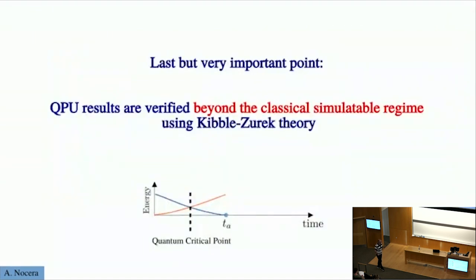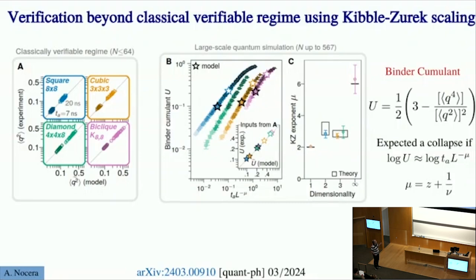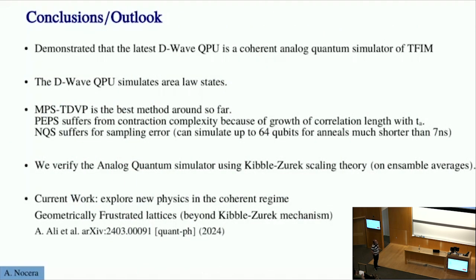I don't have time to go into the details of this. So the last, as I mentioned before, we verified that the machine is working beyond what could be simulated classically, because ensemble averages of Binder cumulants should respect a scaling according to the Kibble-Zurek mechanism. Overall, you are crossing a critical point, and basically we verified that the ensemble average Binder cumulant scales with the annealing time and the system size in agreement with what you expect from the Kibble-Zurek mechanism. And here I can stop and just flash the key take-home messages of this talk. Thank you for your attention.